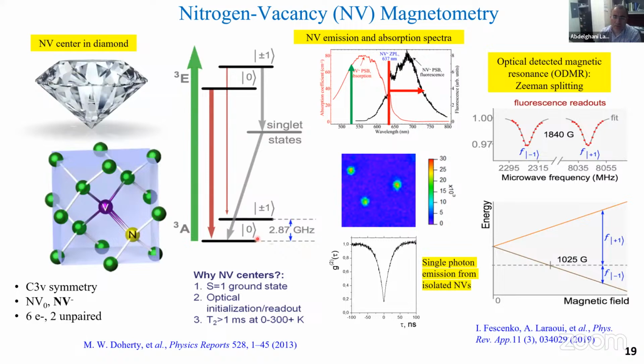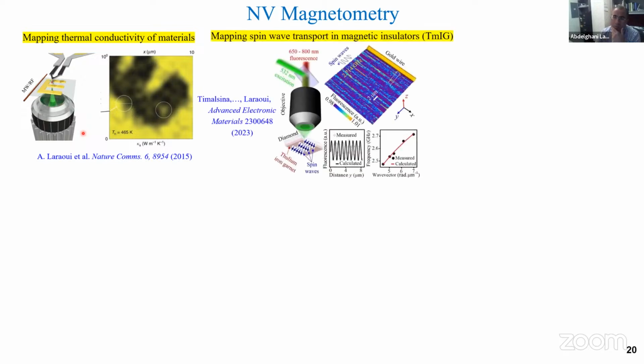In principle, for the Hamiltonian of the system, you have the zero field splitting and the Zeeman splitting term. By engineering the Hamiltonian, you can use the NV for a wide range of applications. You can use it for mapping, for example, in this case, thermal conductivity, as I worked on a few years ago at City College of New York. By looking at the zero field splitting change, you can measure the temperature change in the substrate you are measuring.